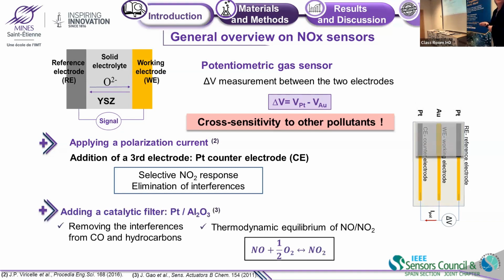The second approach is adding a catalytic filter composed of platinum particles dispersed onto a porous alumina support. With this, we are able to remove the interferences of CO or hydrocarbons, mainly the reducing gases. And we also get the thermodynamic equilibrium between NO and NO2. That means that we have a global NOx response. Combining these 2 solutions, we got a NOx selective sensor.